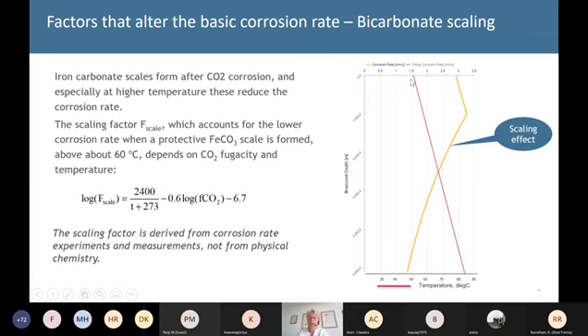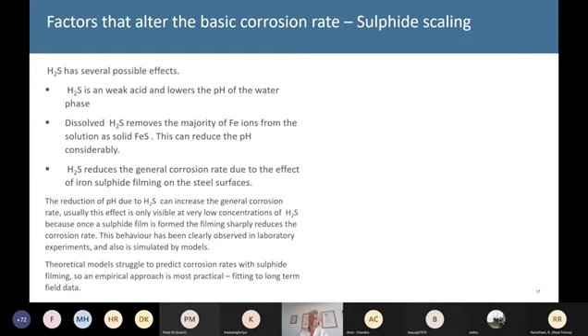So typically in a well, you have higher bottom hole temperatures, and the temperature drops as we come to the surface of the tubing. And the corrosion rate very often follows this pattern, where we've got a higher corrosion rate going to a point, and then scaling kicks in more strongly, and we get this drop off of corrosion rate. So the thing to be aware of here is that the corrosion that you measure at the highest temperature, don't assume that's going to be the highest corrosion you'll ever see in the system. It could be at an intermediate temperature from this, because of this problem.